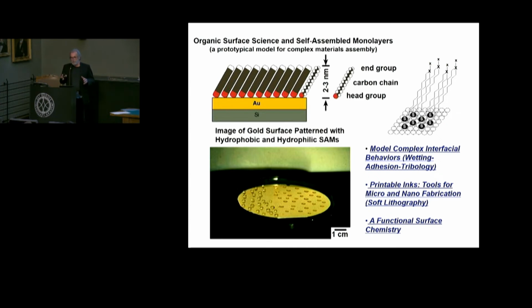And it was actually the way in which you can study the pH dependence of the contact angle in cases where you have protons being donated, as a function of pH change, right? Like what's the effective pKa of the interface, and what kind of perturbation exists as a function of what the composition is, because you make mixed compositions with hydrophobic and hydrophilic, et cetera. So you get this really beautiful functional surface chemistry story that emerges from it. But the picture actually shows that this should be printable, right? Because if you can pattern it by dunking half and half, maybe there's a better thing to do.